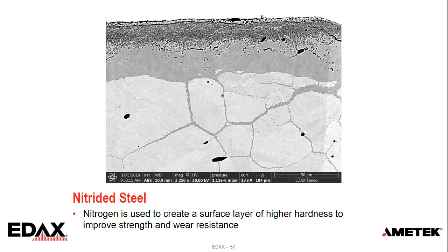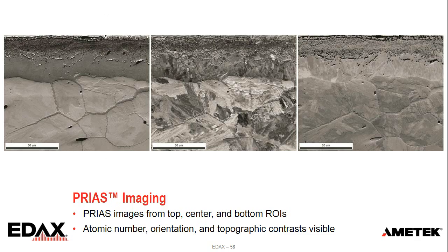This is just an example from a nitrided steel. So nitrogen is used to create a surface layer to create a layer of higher hardness, improves wear resistance. This is just an SEM backscattered image of that structure. And so to characterize this with EBSD, first thing I looked at is what we call a PRIAS image. The PRIAS uses different regions of our detector to create different contrast mechanism images.